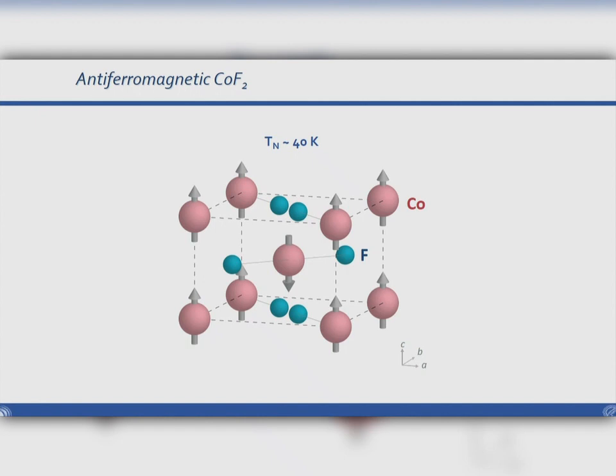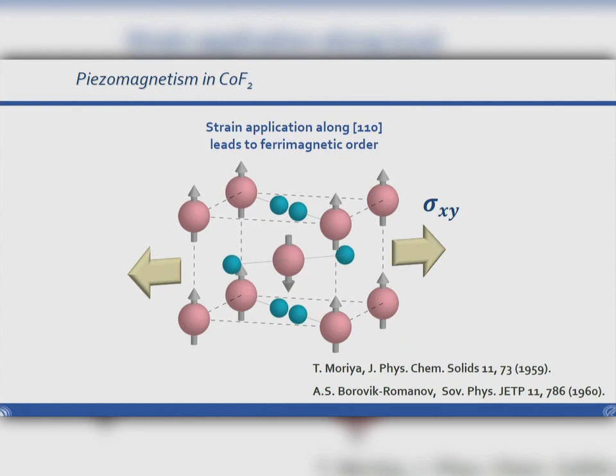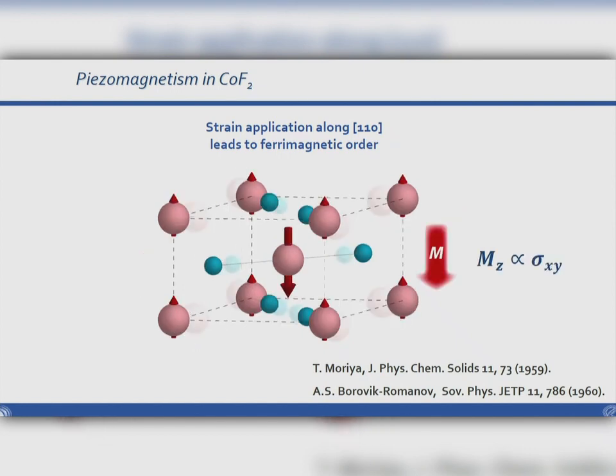But now let's come to the experiment that is probably most interesting for you, which is done on the antiferromagnetic cobalt fluoride. As you may well know, this crystallizes in a rutile structure, and the cobalt atoms arrange on a BCC lattice, and below the Néel temperature, which is 40 Kelvin in these systems, you find a perfectly balanced antiferromagnetic system. So we have two cobalt sublattices, two magnetic sublattices, one that results from the cobalts in the center and one from those on the corner of this cube. So this is perfectly balanced. But at the same time, this material is piezomagnetic, which means that if you apply strain along the in-plane direction, you can induce a net magnetization that is proportional to the strain that is applied to the sample.